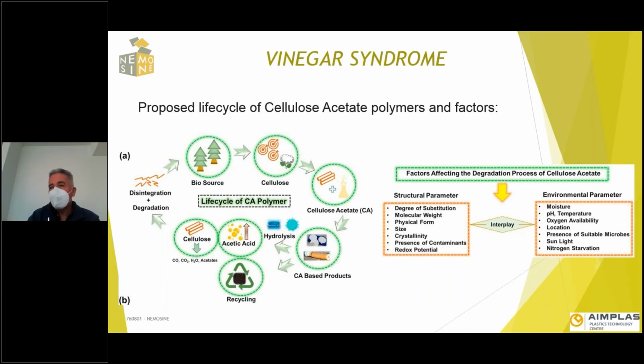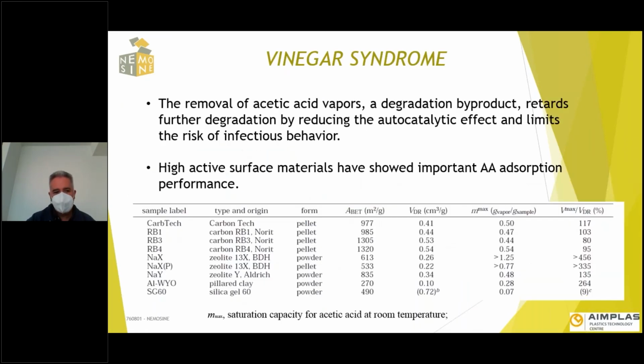And finally, the objective of using this kind of package that we are developing in the NEMOSINE project, with acetic acid adsorbents, is to reduce the speed of the reaction and to allow a reduction of the environmental requirements in terms of temperature, in terms of humidity, and more. As I have said, from the beginning, talking about acetic acid sorbents, several important classical materials such as zeolites, active carbons, or silica gel have been used. Here in this table, we can see several values of the performance of acetic acid absorption. For example, we can see that zeolite has an important performance related to acetic acid absorption.